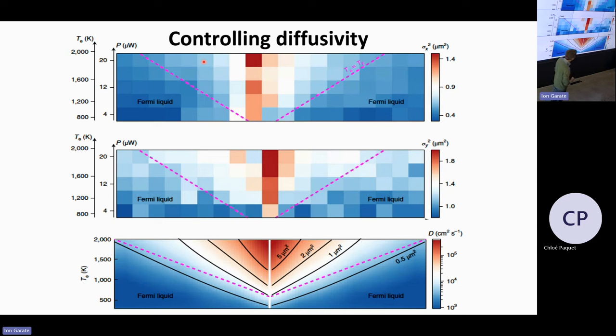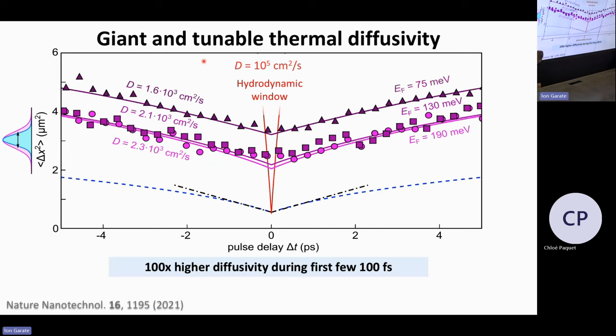diffusivities that are well beyond 100,000 centimeters squared per second. So this is more than two orders of magnitude larger than the diffusivity that you get in the diffusive regime. So just by being very close to the Dirac point and by having the situation where the interaction is mainly among the electrons and without interacting with the phonons, you get a situation of very, very fast broadening, very fast diffusion of electronic heat. So that is then the picture we have.